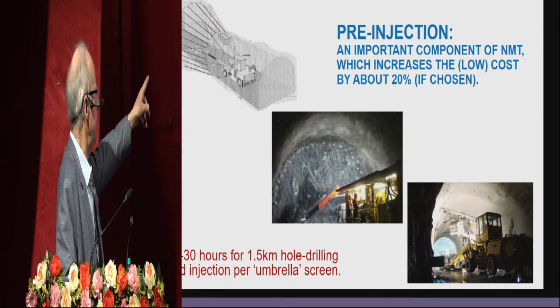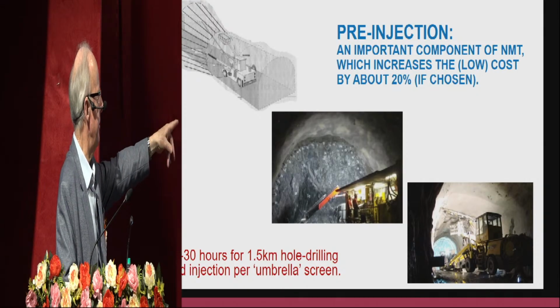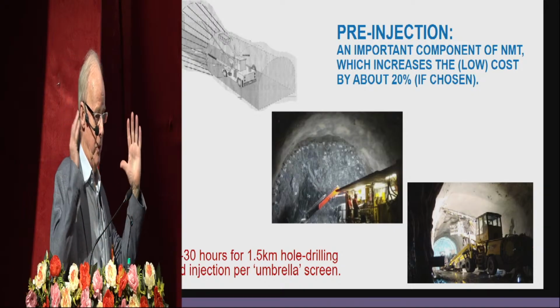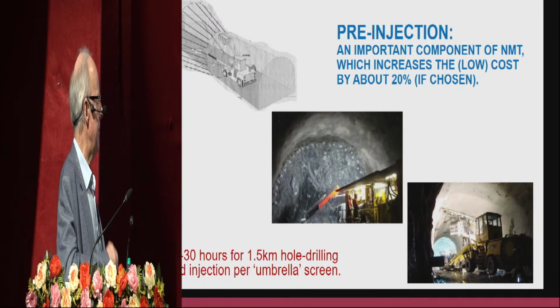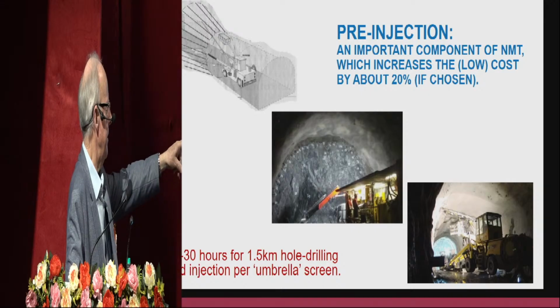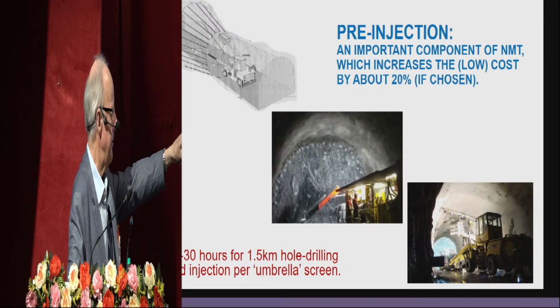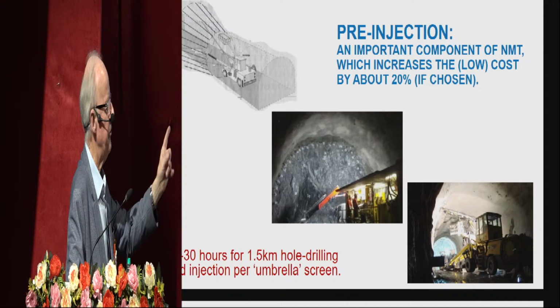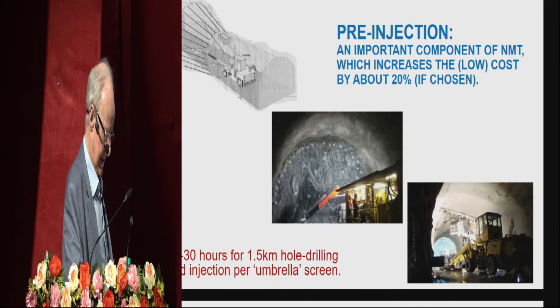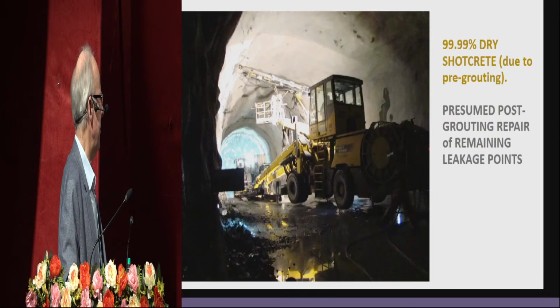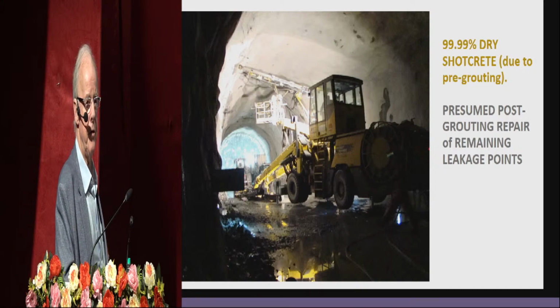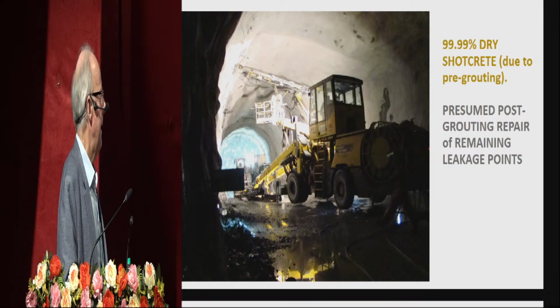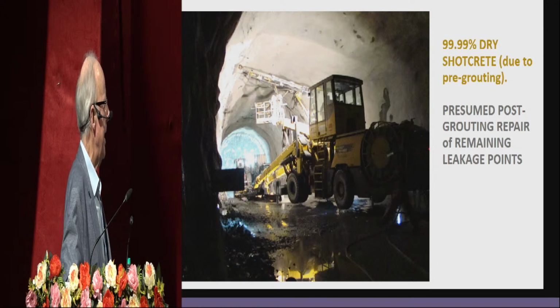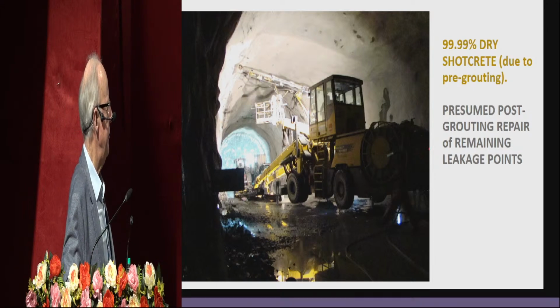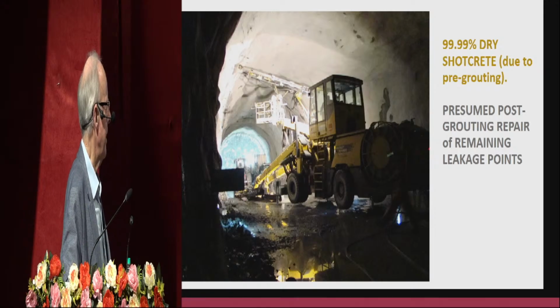So you see the umbrella, you see about 70 holes in this big high-speed rail tunnel. It should be much more like an arch. It's been squashed out. And there you see the last 70 or 80 meters in that tunnel. I think they're doing a post-injection of 1 leaking hole. But basically, it's sort of dry shotcrete if you do the job properly. So there I've written 99.99% dry shotcrete due to successful pre-grouting.